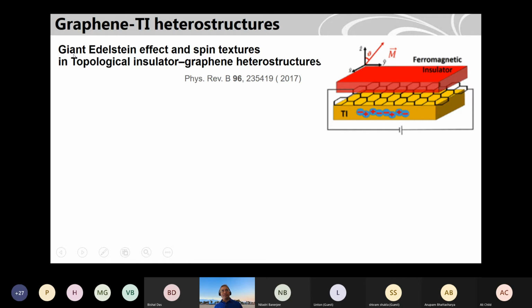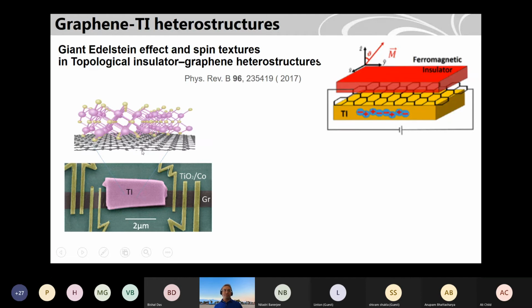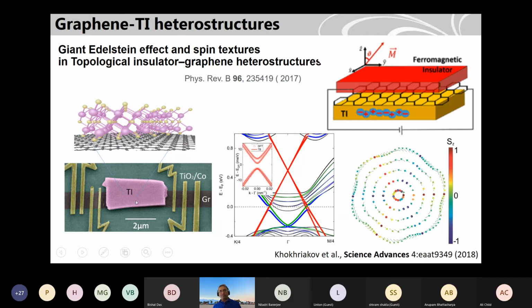So it is also expected that you improve the spin-charge conversion by putting graphene, because graphene is a good medium for spin transport. And we have done that experiment by putting a topological insulator on top of a graphene channel here, similar to what I showed in the previous lectures. We send a spin current in this heterostructure and try to detect it on the other side. And we can see what the spin-orbit coupling is in graphene due to the topological insulator.